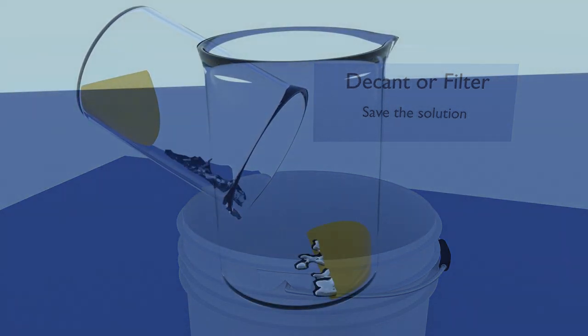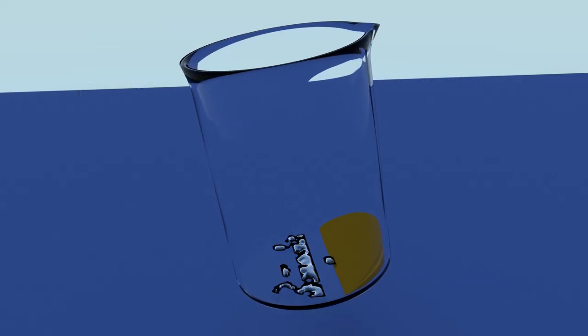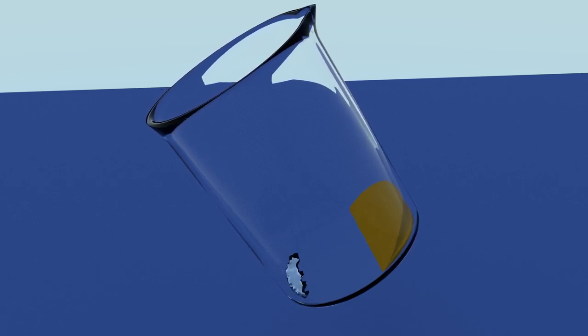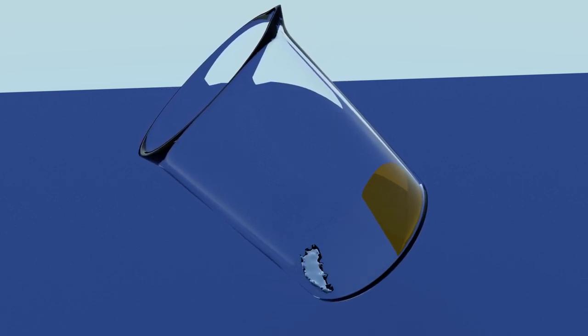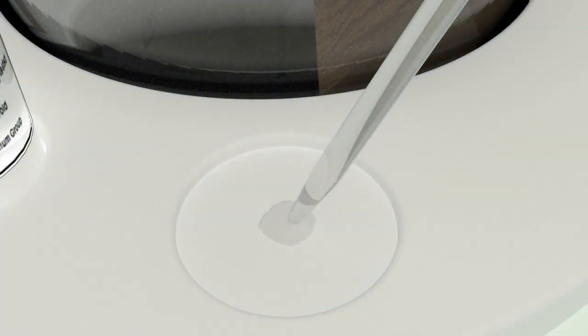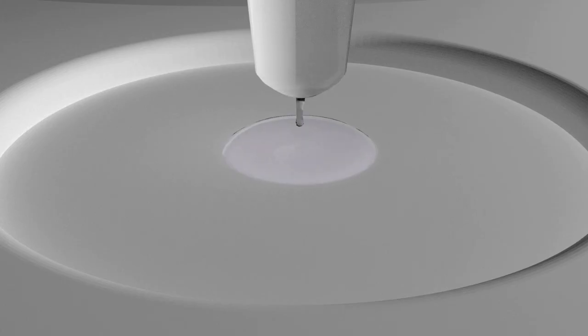A small amount of water will cling to your gold mud. We'll take a few drops of that water and test it for impurities. Tilt your beaker. Water will drip off the mud and then puddle in the corner of the beaker. Take a sample from the puddled water and place it on a spot plate, mirror, or paper towel. Two tests. Add a drop of ammonia test liquid. If you see any color change, even the palest shade of blue or purple, rinse again and then test again. When the ammonia test indicates no color change, it's time to give your mud a final rinse with distilled water.